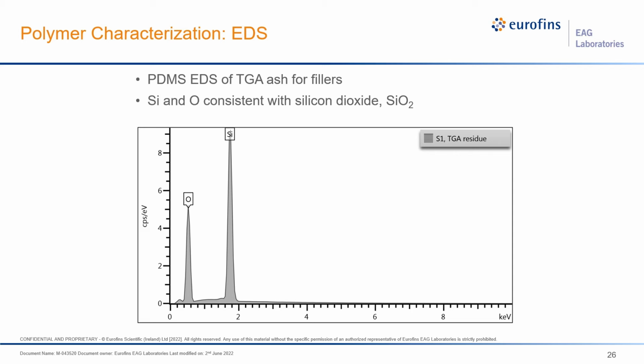Some of the overlap in these elements is also present in PDMS, but PDMS can't survive at these temperatures. So the presence of silicon and oxygen is consistent with silicon dioxide, or silica. And so this is what's used to fill the polymer. What's not shown here is we also ran a pure PDMS standard alongside the sample, and after heating it to 800 degrees, only 0.5% of the sample mass remained. This gives us further confidence that we're indeed detecting a filler and not just oxidizing the siloxane species to silica.